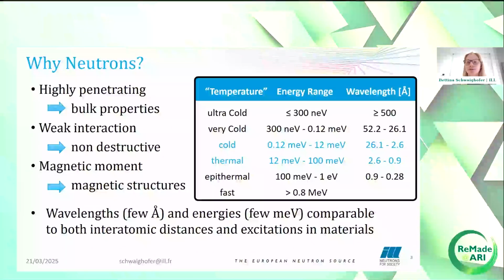Neutrons are a really good probe for the bulk of materials. They interact with the nucleus instead of the electron cloud, and therefore can penetrate matter quite well. This also means that neutron scattering can be done in complex sample environments, for example, in situ measurements, in cryostats and pressure cells. The interaction of neutrons with matter is weak, which is particularly beneficial for soft matter because it's a non-destructive method.